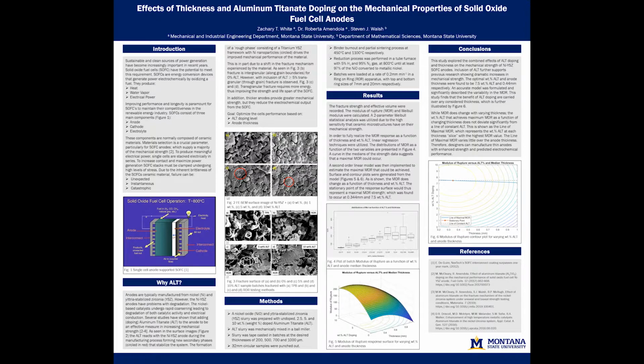If we observe the surface in Figure 2, we can identify the formation of two secondary phases, referred to as the rough phase and particle phase. These phases consist of newly formed titanium YSZ framework, the rough phase, with nickel nanoparticles also developed as the particle phase. The nickel nanoparticles provide added ductility to the framework and increase the strength of the material by shifting the fracture mechanism responsible for failure.